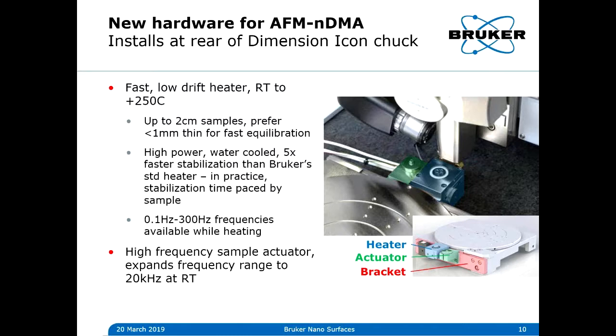For variable temperature measurements, a new low drift heater has been developed to optimize the accuracy of collocation of the spectra and the images, and also to reduce the time required to stabilize the system when changing temperature. So this is our low drift heater on the back here of the chuck, and then we also have this over here, a high frequency actuator. This can allow you to extend your frequency range. If you'd like to go above 300 hertz, you can go up to 20 kilohertz at room temperature with that high frequency actuator. Both the actuator and the heater are conveniently attached to the back of the chuck, so they are out of the way when you're working with larger samples.